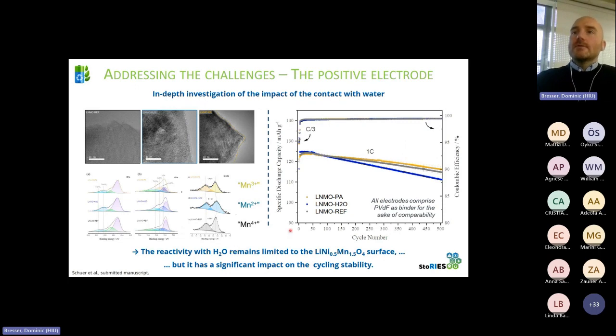We processed all these materials with NMP and PVDF into electrodes, as also briefly mentioned here. And then you can see the difference there, right? The bulk might not be affected, and the surface effect might be very, very limited in terms of thickness, but still you see a significant effect on the cycling performance. You see that the reference here in gray is performing pretty well, I'd say. This is 500 cycles.